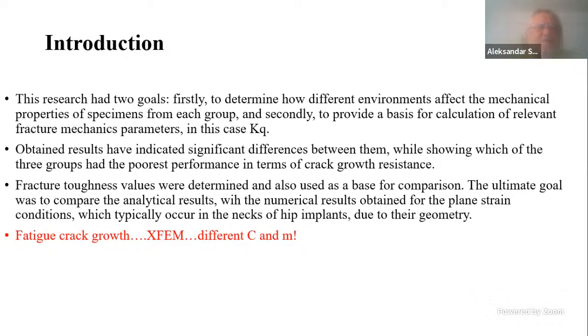So as for the introduction, I think I mentioned most of the important facts. Let me just say, and you will see it soon, that we did have a problem with the fracture toughness testing, because we had only 2.2 millimeters of plate thickness. So we couldn't get K1C, but anyhow, the basic idea here was to compare. And from previous experience, we also knew what value K1C would really have.